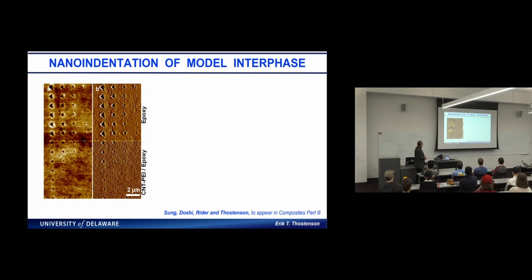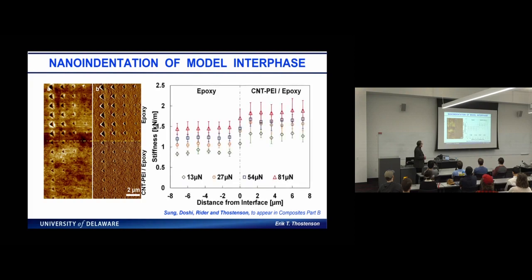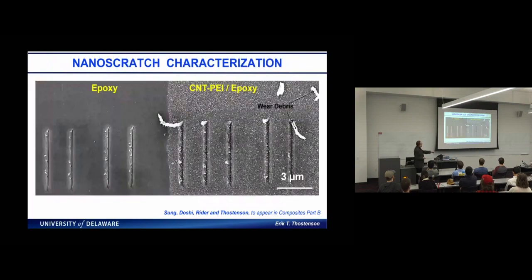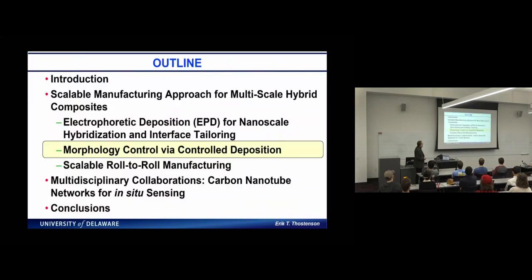And here you can see there's significant stiffening. You can see the indentation depth as we move across that epoxy nanotube interface. Significantly, we're changing those properties at the very micro scale, and that affects the macro scale properties. This is also where we did some nano scratch, and you see the indentations or the scratches in the epoxy. And you can see this of the nanotube epoxy. You see the significant amount of debris, as we're significantly increasing the fracture toughness in that area.